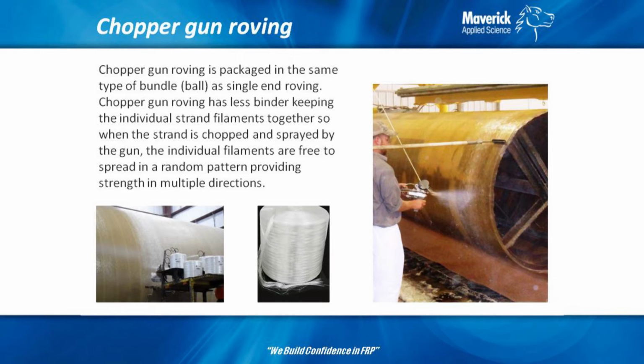Chopper gun. There's a lot of different ways to apply chop. This is a basic ball of chop that you see here sitting on the carriage, and the spray is coming out right here. So there's one strand run through a gun. It's easier to see here, I guess. The strand runs through the gun, is chopped into random length pattern, and then resin is sprayed along with it to basically make chop strand mat, wet chop strand mat as it goes along.